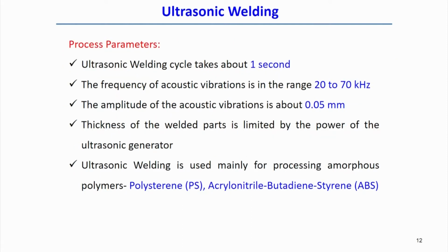Let us see what the process parameters are in the case of ultrasonic welding. The ultrasonic welding cycle takes about 1 second, a very small time as compared to the other welding processes. The frequency of acoustic vibration ranges from 20 kilohertz to 70 kilohertz, so very high frequency vibration is created in this process, and the amplitude of the acoustic vibration is very small, only 0.05 millimeter, or 50 micrometer.